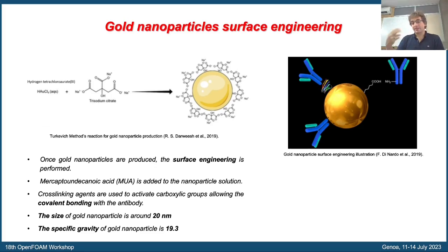And the second ingredient of the technique: by photoacoustic imaging, it's possible to compute the concentration of golden nanoparticles and it detects the position of the potential atherosclerotic plaques much earlier than the plaque will form completely. These golden nanoparticles are small enough, 20 nanometers as you see, not to be recognized by the immune system.